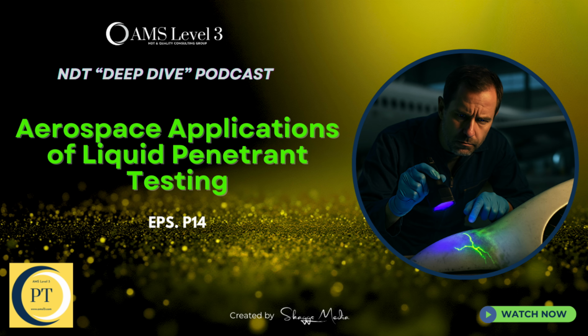Let's talk about the common types. What are the specific requirements for non-aqueous wet developers, the ones that usually come in a spray can? Non-aqueous wet developers have to be applied as a uniform, thin coating. The key word there is thin. If the coating is too thick, the developer itself can actually mask the indications. It creates this dense layer that the faint fluorescence can't shine through. And if that happens, back to square one. Clean and reprocess. The development time is also tightly controlled. A minimum of 10 minutes, but a maximum of 60 usually.